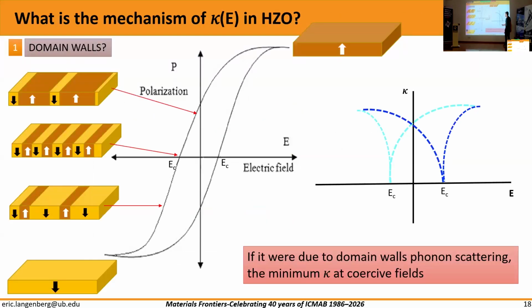Okay. But then the question is, what is the mechanism behind that? Because I was telling you before that domain walls are related to scattering phonons: high density of domain walls, low thermal conductivity; no domain walls, high thermal conductivity. But if it were like this, our thermal response should be something like this. Okay, this is a very naive drawing, but the minimum in the thermal conductivity should be at the coercive fields, because at the coercive fields is where we have the highest density of domain walls. And we don't have this picture.